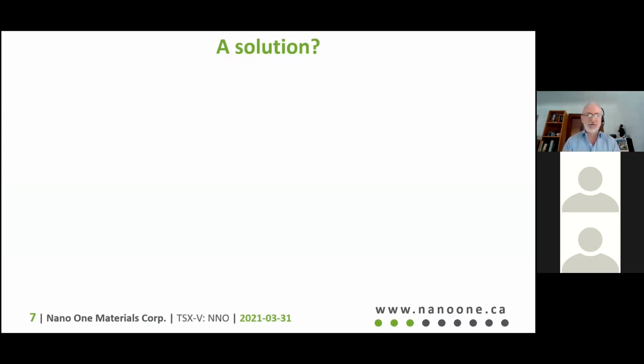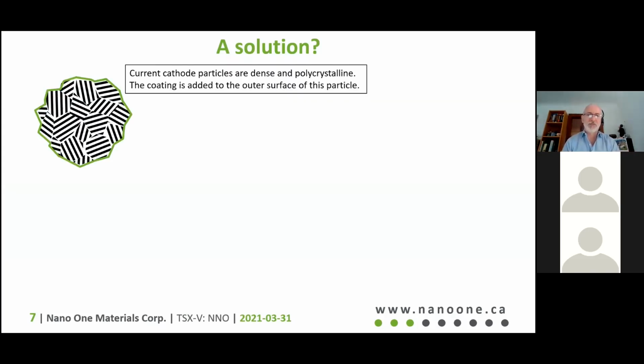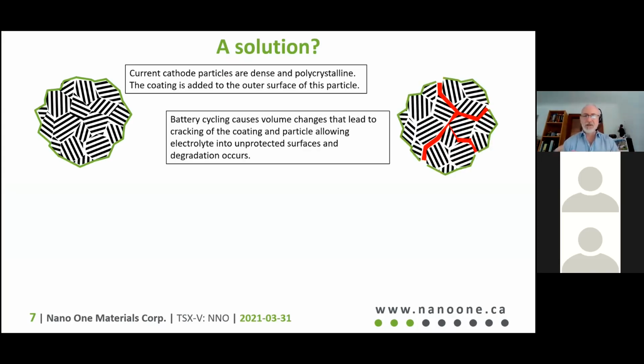So to recap, the problem currently is that cathode particles are dense, polycrystalline balls, if you like, and the coating is added to the outside, like a sugar coating around the whole particle. But as you cycle the battery, the cathode material expands and contracts. As the lithium goes in, it expands, and as you take the lithium out on charging, it contracts again. And this breathing of the particle fractures it and fractures the coating, so it allows the electrolyte inside the particle, which is unprotected. And so you get faster degradation, and the effectiveness of the coating is compromised.